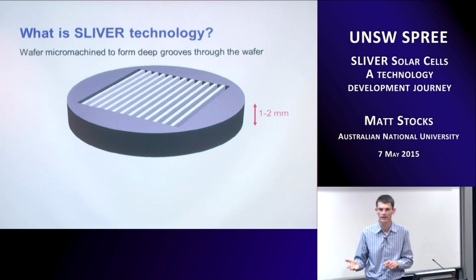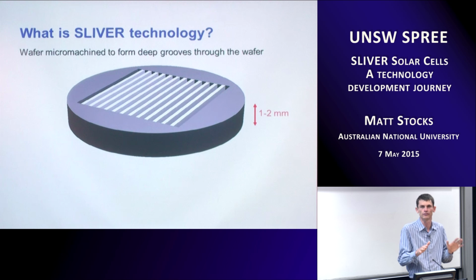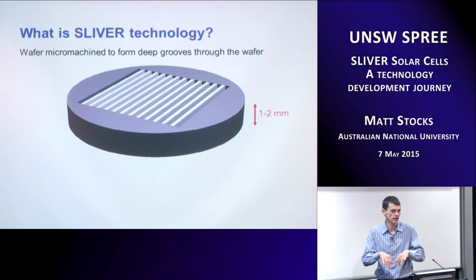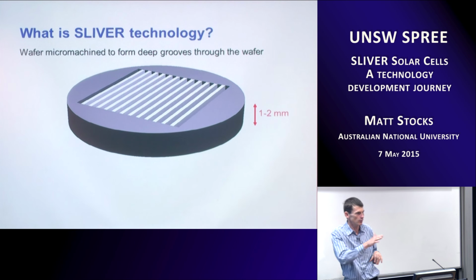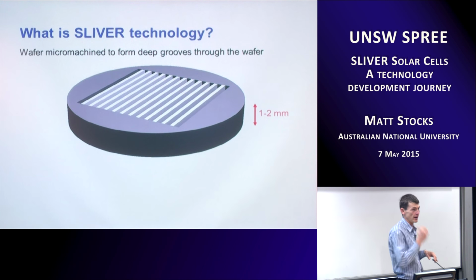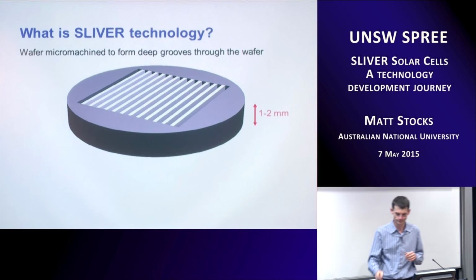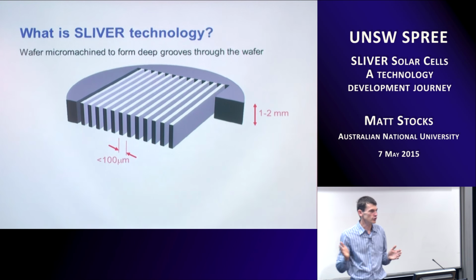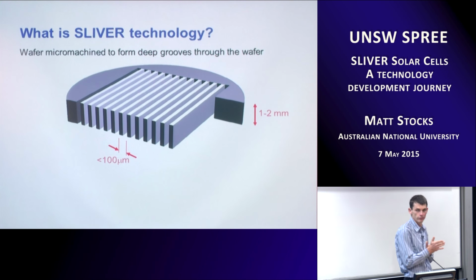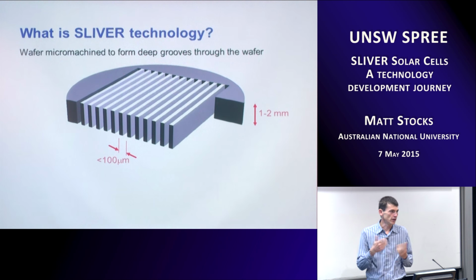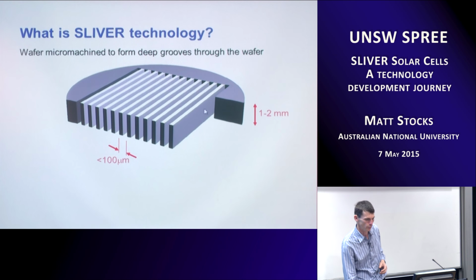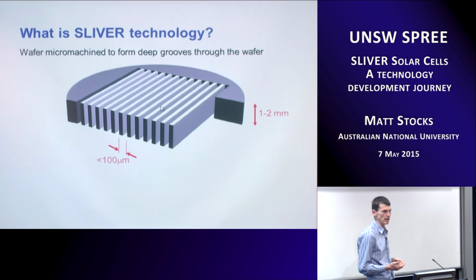And we use it all the time for our standard solar cells. If we take a 100 silicon wafer, we etch it, we do the random texturing process. And what we're doing is we're creating these 111 planes all over the surface, which don't etch, in comparison to the 100 plane, the downward plane, which is etching. So what we've done with SLIVER technology is we've rotated our wafer on the side so those 111 planes are vertical. And so we can etch very, very deep grooves, which are 100 times deeper than they are wide. Okay? So if we can do that cutting at a very narrow pitch, something of the order of 100 microns or less, then we can get these strips of silicon forming within our wafer. And this is what we're interested in making solar cells with SLIVER.